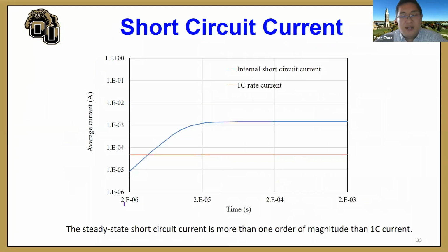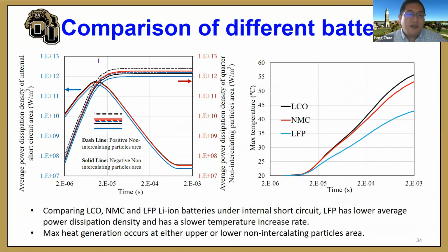And what we found is that during a typical internal short circuit, the current can be 1 order of magnitude higher than the 1C rate current, which is the current corresponding to a full charge in 1 hour. And also we have shown that in the beginning of the internal short circuit, the maximum heat release comes from that piece of metal. After that, the maximum heat release comes from the non-particle intercalating regions at either side of that piece of metal. And we also compared different battery materials. We found that lithium phosphate, under the same condition, can have the lowest temperature rise during an internal short circuit. So that means this lithium phosphate battery has the potential to be safer.